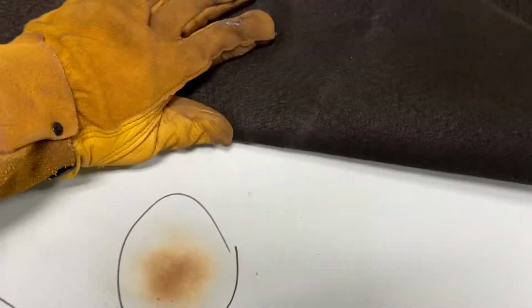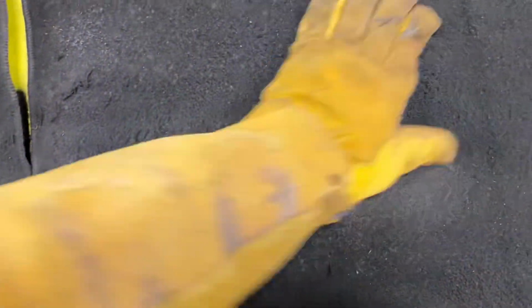The 3-layer one, even here where we held the torch for 30 seconds straight and just destroyed that top layer, I still got a layer of fiberglass. And it still hasn't melted through my backside yet. Now here's where we hit it with the plasma cutter. Yeah, it's ate through it pretty good, but we got one spot there, one spot there where you can start to see the fiberglass mesh, but no holes. You know, there's the back side of that one.